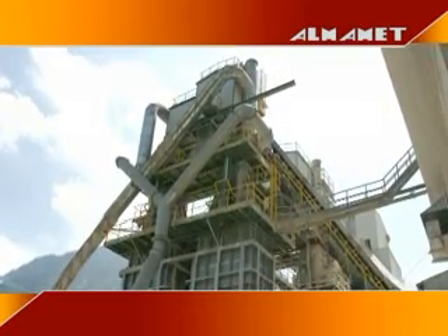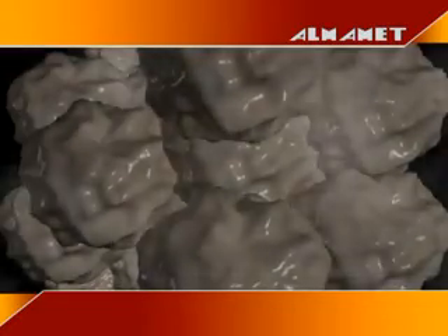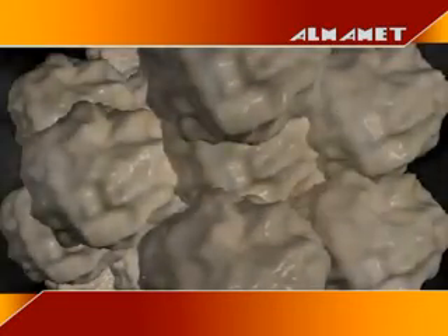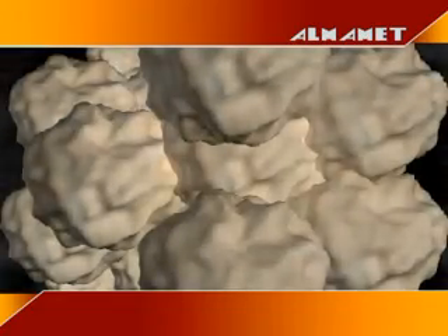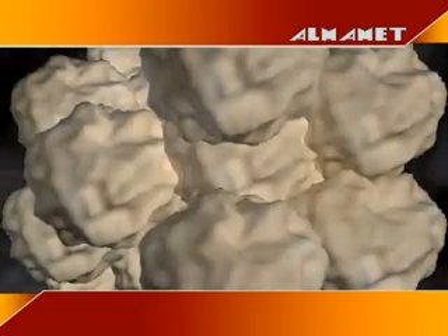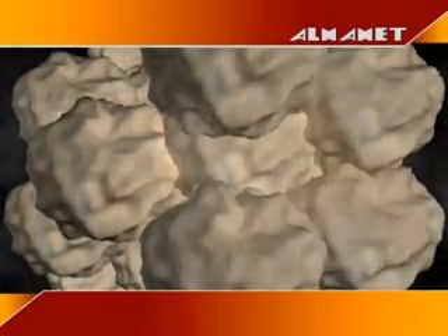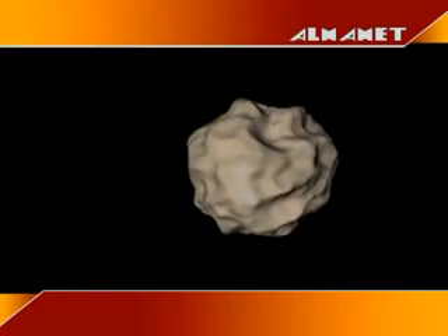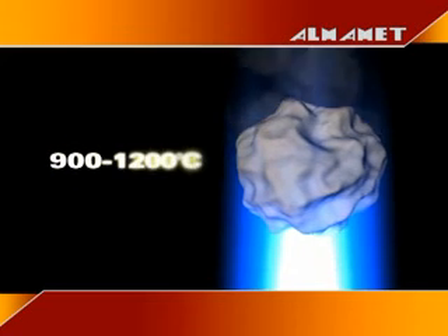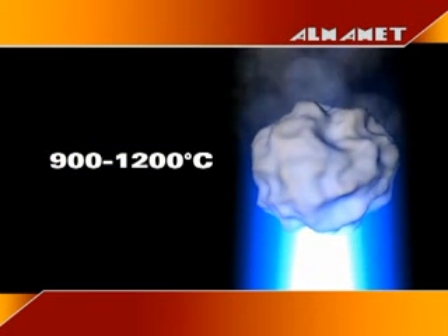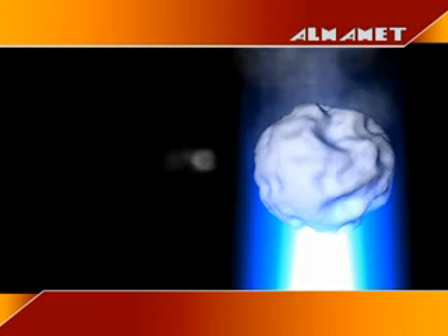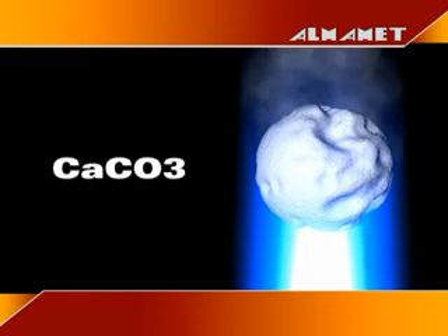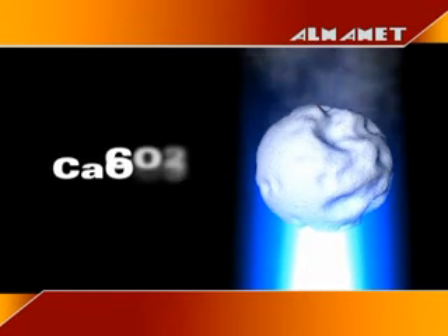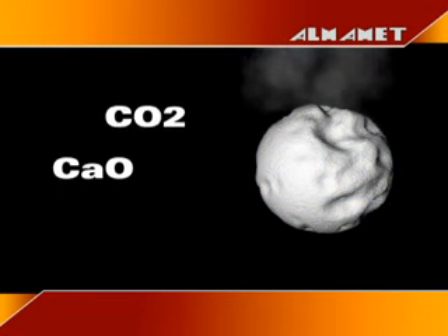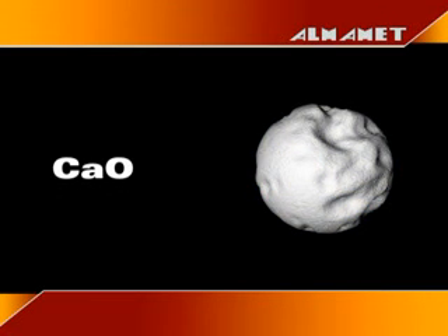The kiln stands vertically in the shape of a cylinder. The first phase occurs in the kiln's top section and consists of heating the limestone with hot gases from the firing zone to remove moisture. The pieces then slowly slide into the firing zone, where they are heated between 900 and 1200 degrees Celsius. In this fashion, limestone, or CaCO3, is broken down into calcium oxide, CaO, and carbon dioxide, CO2.